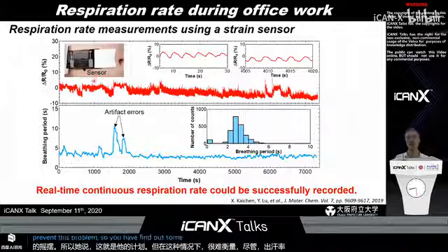So to prevent this problem, we applied some Kirigami structure to reduce the strain on the sensors, so that we can monitor the perspiration rate for a long time without fluctuation or large hysteresis problems. Based on that result, we extract the breathing period, which is around 4 seconds between each breath. That is very standard for standard adult breathing rates.